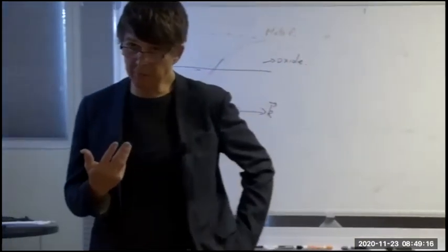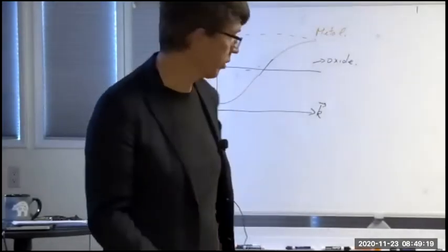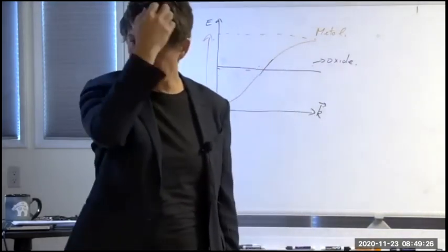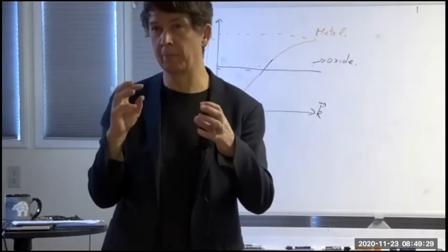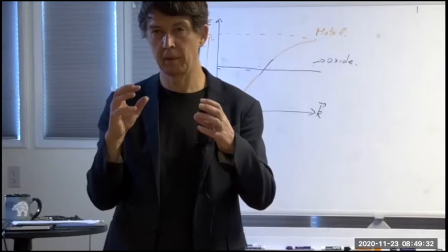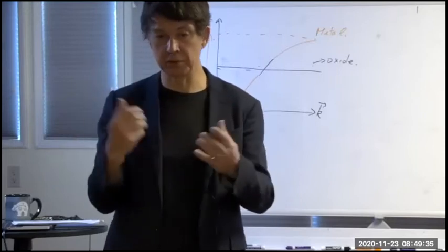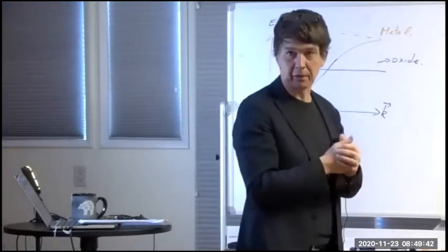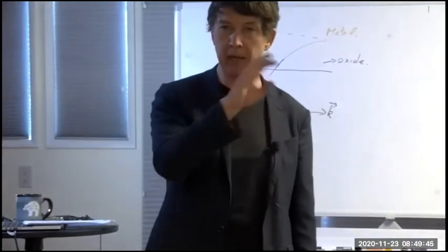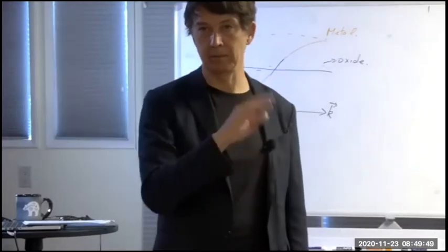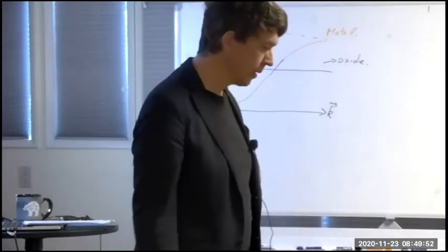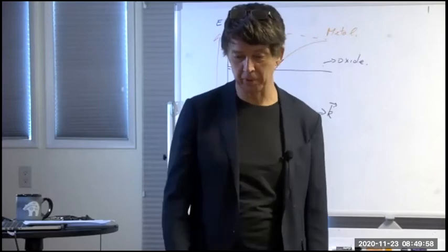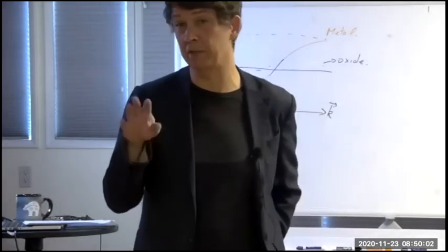What happens is that the band picture is wrong, right? You have no Bloch states anymore. When you have no bandwidth, that means I have essentially extremely small overlap between orbitals. It's almost non-existent, which means electrons don't really tunnel from state to state. What is hybridization? What makes bands? It is tunneling, right? If an electron tunnels really fast from atom to atom, you get bands, and you get this metallic-like conductivity. If you start crimping down the bandwidth, which is the orbital overlap, the tunneling rate goes down and down and down. And at some point, what happens?